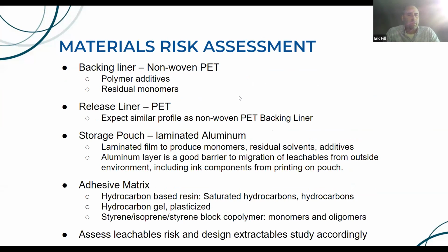So the first thing we did for this study, again, was a materials risk assessment. We looked at the backing liner for this product. It was a non-woven PET. We knew from that PET we could have polymer additives, we could have residual monomers. We knew what those were. We documented those. We also looked at the release liner, also PET, and we expected that it would have a similar profile as that non-woven backing liner.